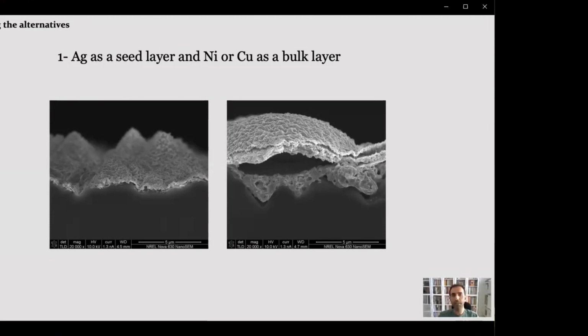It is also hard to print narrow grid lines with these methods. It is also reported that there might be some delamination between two metals, like you see in this picture, between silver and the bulk layer after the firing process, and fill factor suffers from high resistance, high grid line resistance.